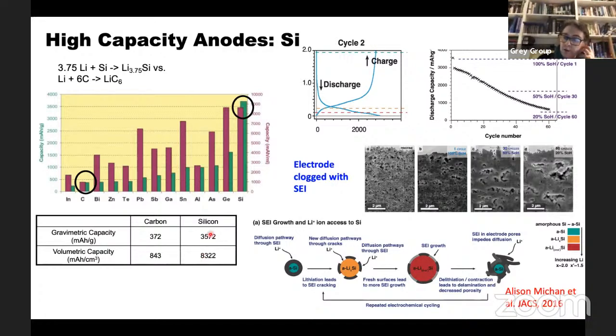And that gives you an overall at least 50% increase in energy density on your battery if you look at the full cell. The problem with silicon is the problem that I talked about before, and that's the idea of this electrolyte decomposing and forming SEI. And so this is a picture from our work where we have an original electrode structure, and at the beginning, this is the pristine material. You can see it's holey and porous, and we're doing that because this material expands by about 300% when it reacts, and that's simply because you're adding so much lithium. So you need some space to allow it to accommodate that expansion.